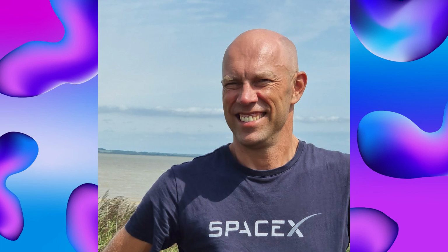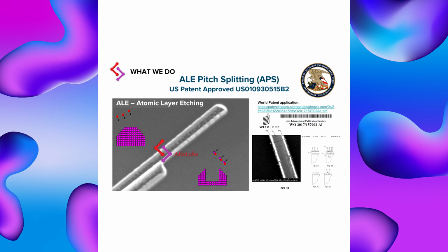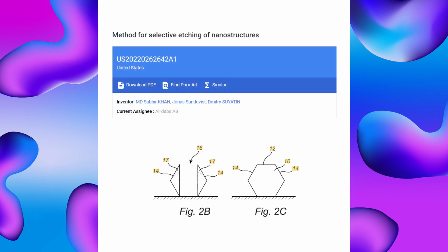ALD Stories is happy to welcome again Jonas Sundqvist to the show for an unprecedented third time. This time, Jonas is here to talk to us about his company AlixLabs and their groundbreaking new technology, ALE pitch splitting, or as they abbreviate it, APS. Now, this recently patented workflow is based on an atomic layer etching process which exploits a newly discovered topographical selectivity, where surfaces perpendicular to incoming plasma etch faster than those at angles.